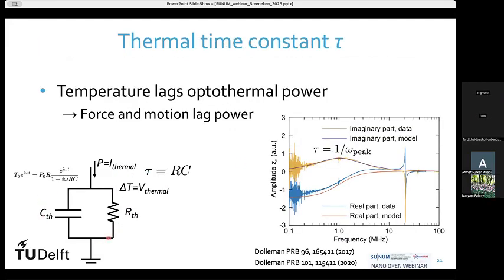You can model it by an RC system where this tau is the RC time. So this temperature increase occurs a little bit later compared to the increase of the laser power. This thermal time constant tau we can measure from our frequency response measurements. If we look at the real and imaginary part of our response, the time tau is characterized by a peak in the imaginary part of our experiments, which is shown here. We can convert the frequency of this peak to a time, and those times are in the nanosecond range.